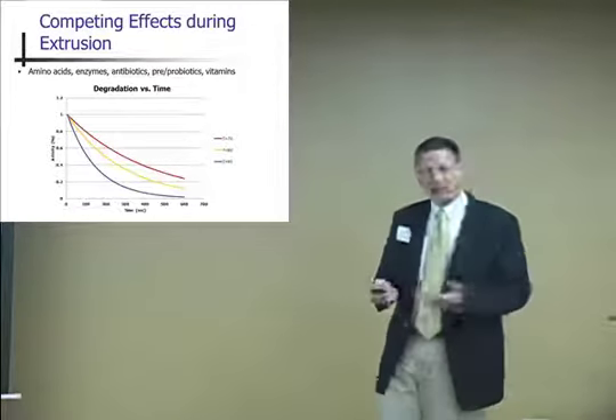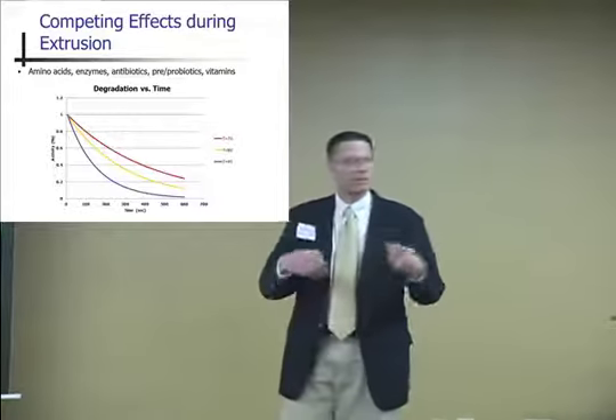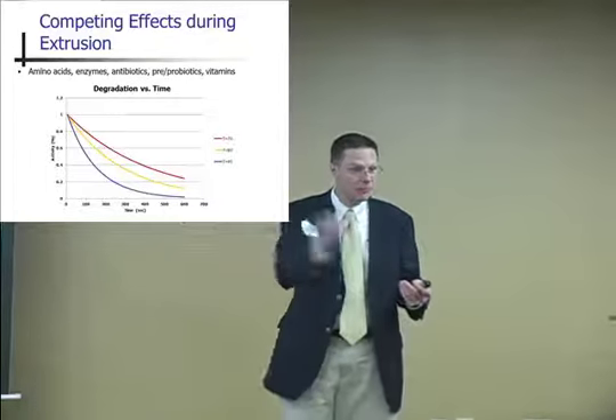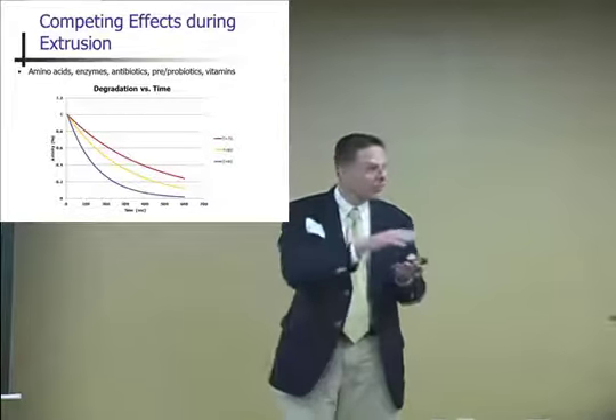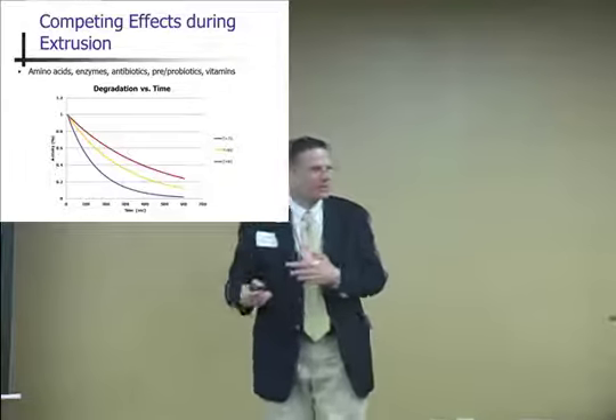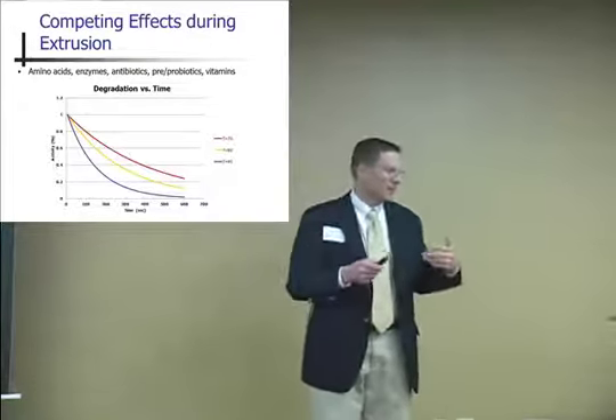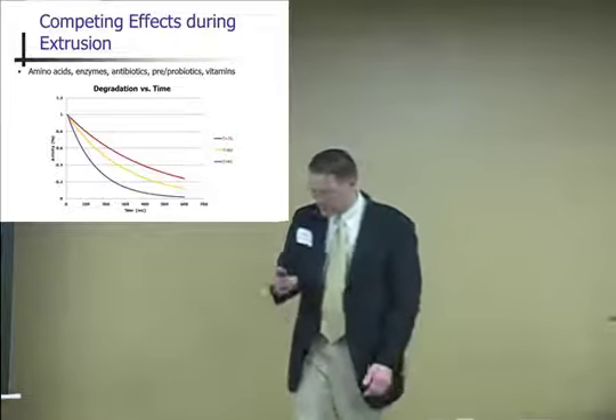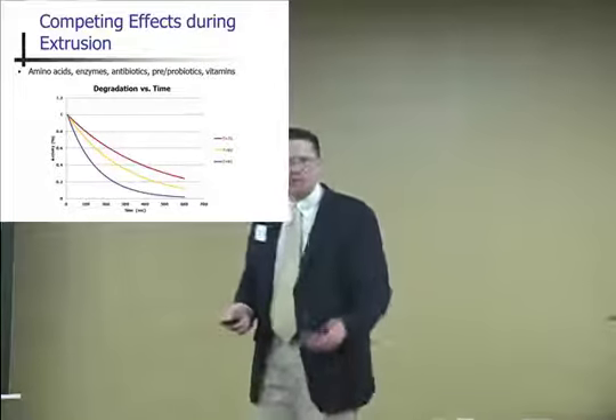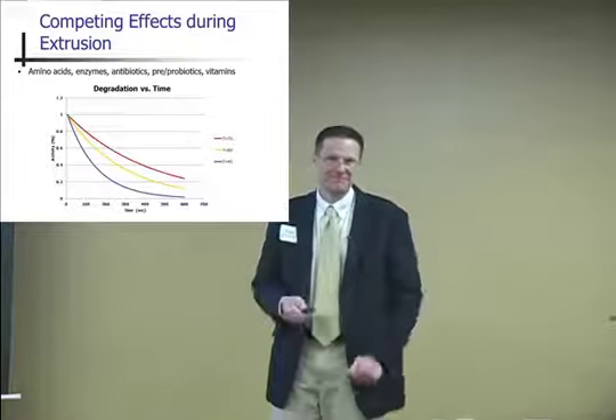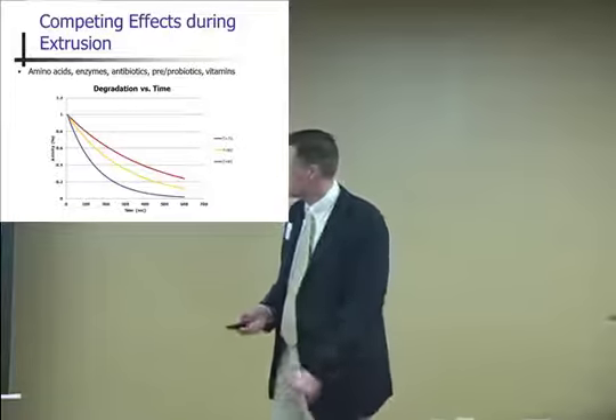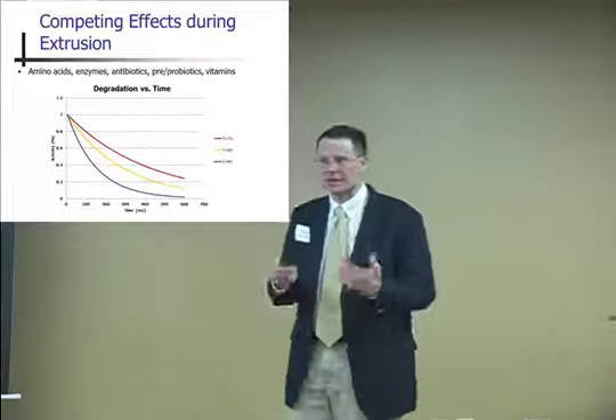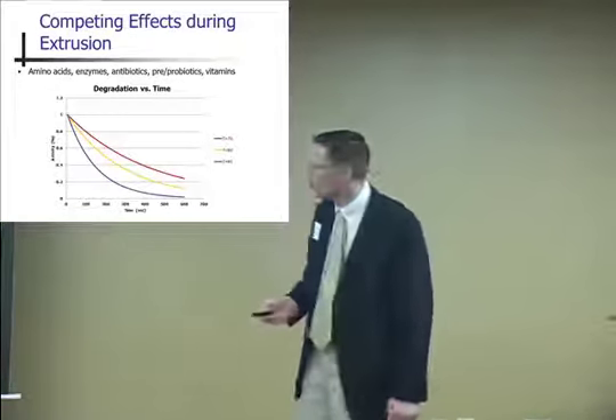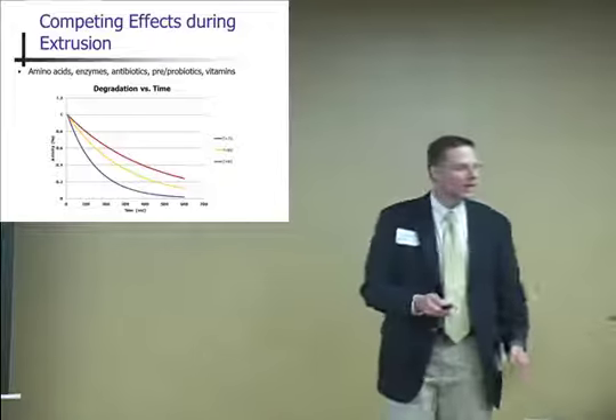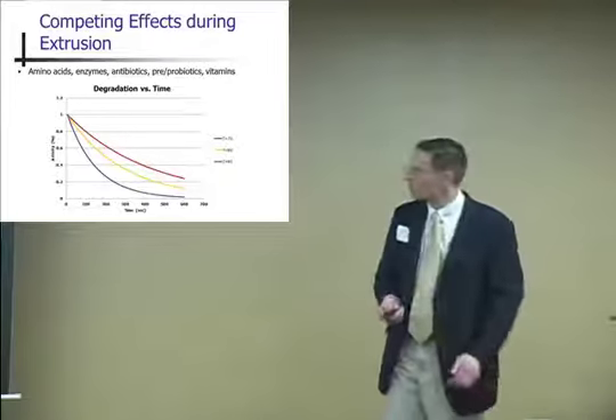So ideally, you shut the temperature off and let the material flow through the extruder so you minimize your temperature increase. But the trade-off is you're not going to have expansion, you're not going to have cooking, you're not going to have gelatinization. So how do you get the right answer? It truly is a juggling act because you need some temperature to get the job done, but you don't want to totally degrade the materials that you're trying to transport to the fish.